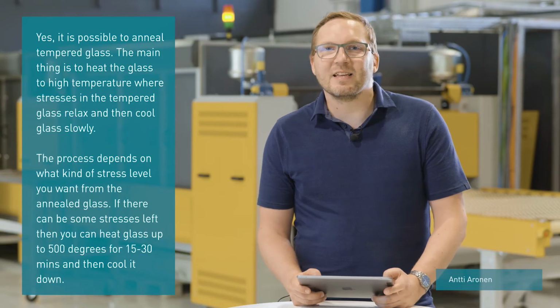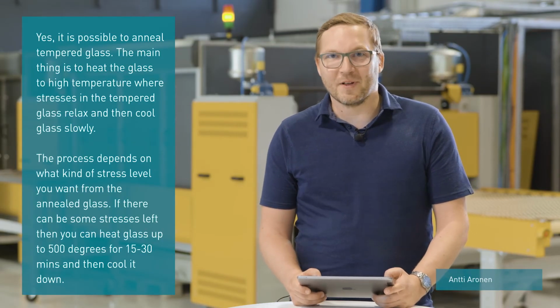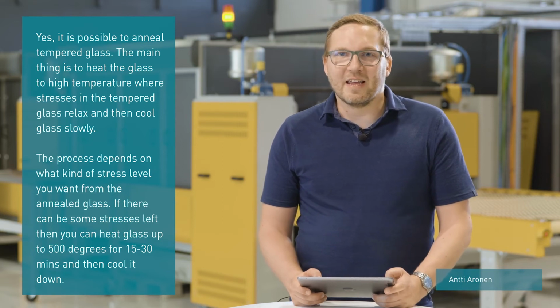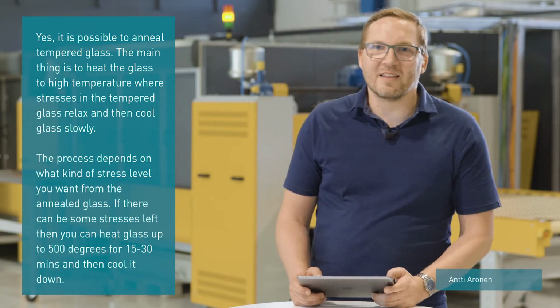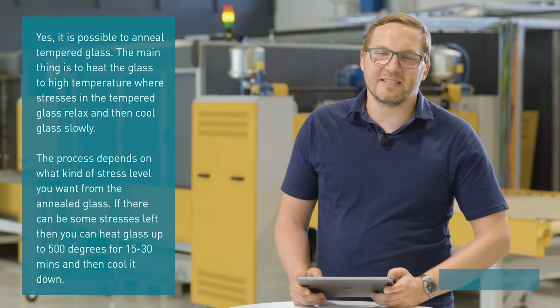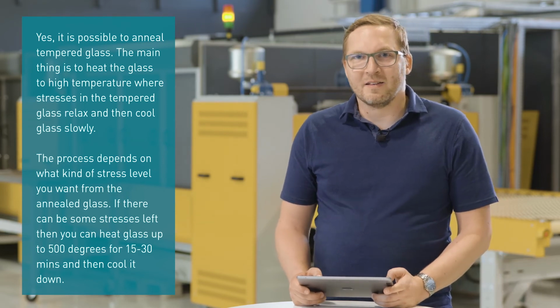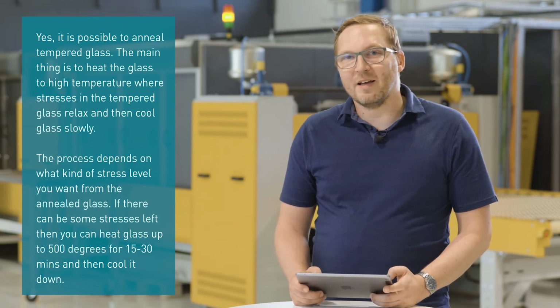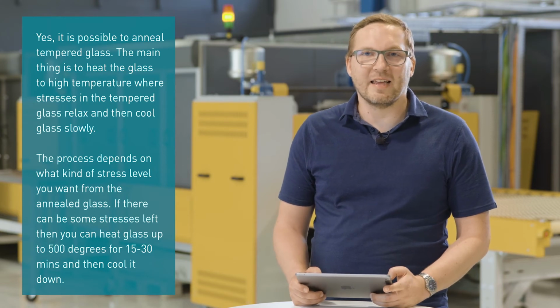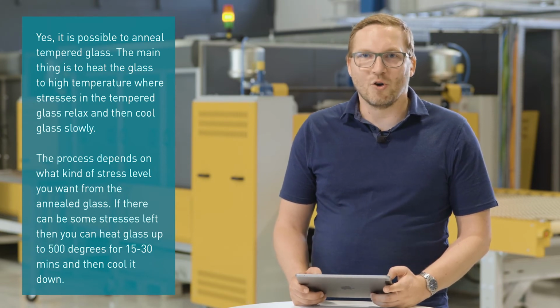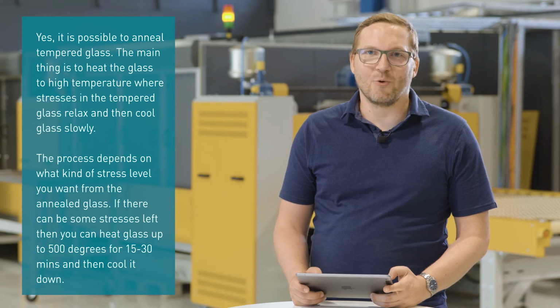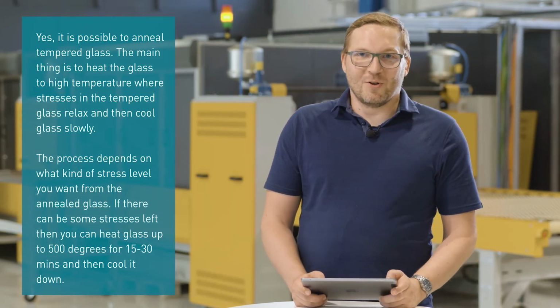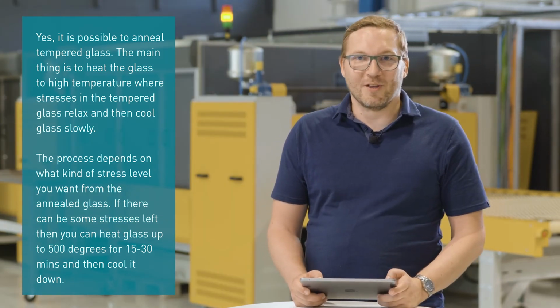Yes, it is possible to anneal tempered glass. The main idea is to heat the glass to that high temperature that stresses relax. So you have to heat glass up to 500-600 degrees and then cool down slowly so that glass doesn't break during the cooling. The process depends on what kind of stress level you want.